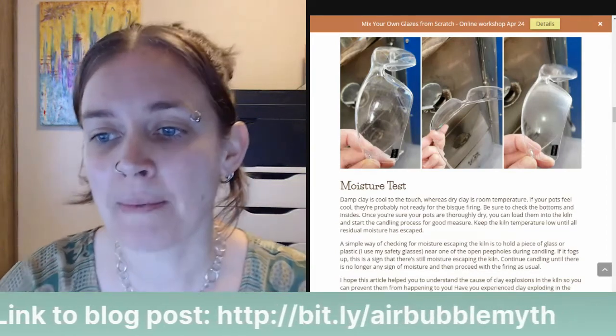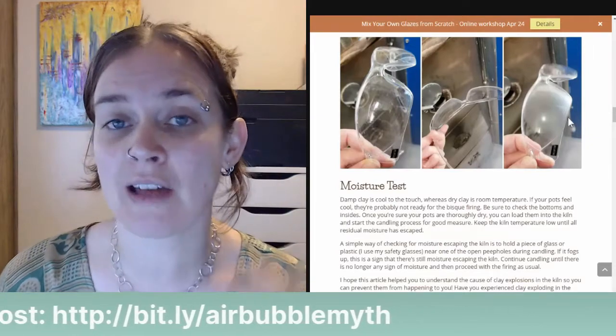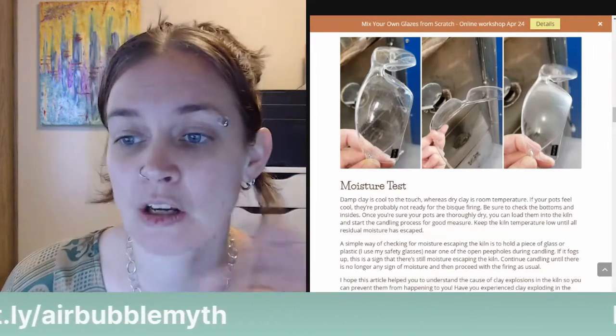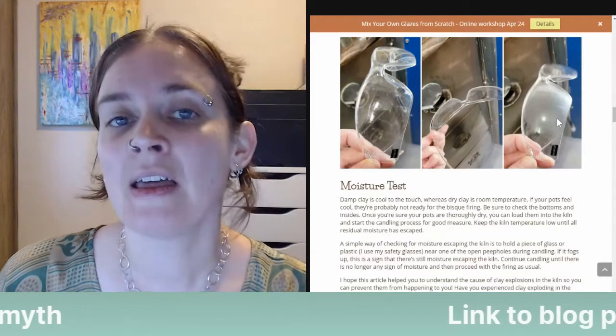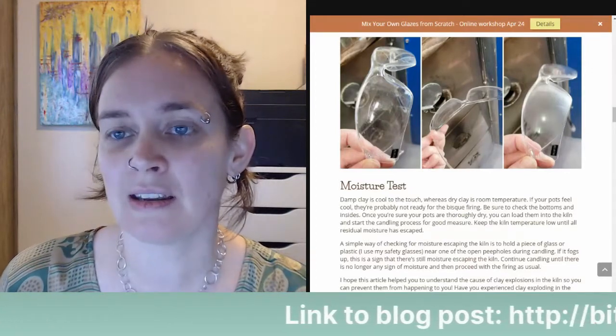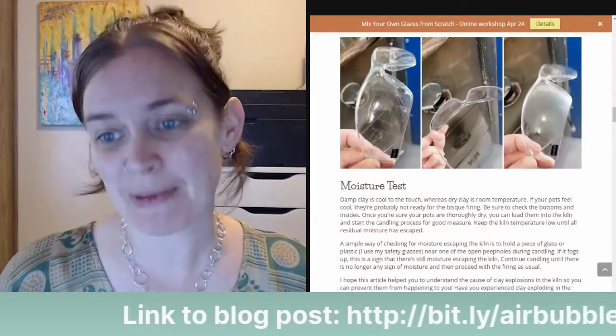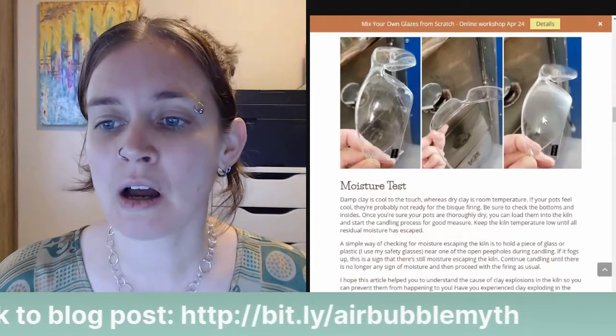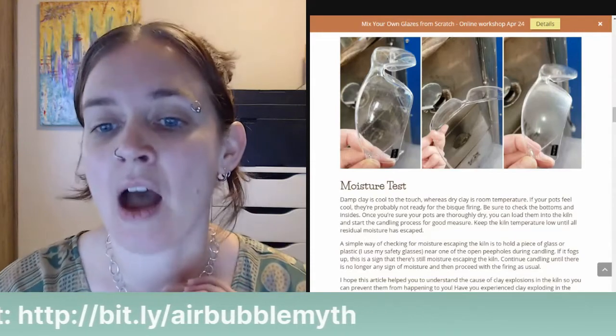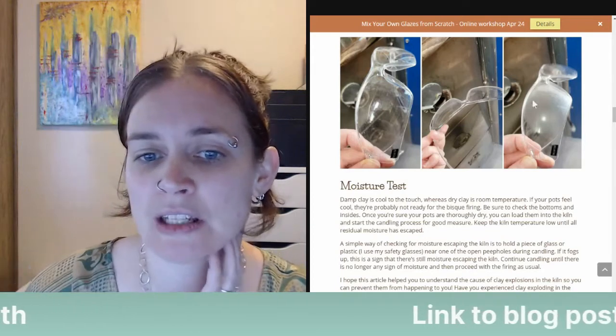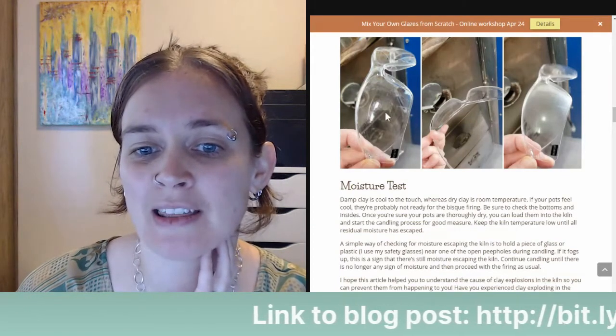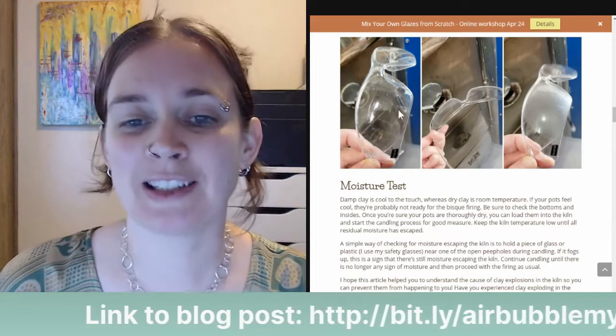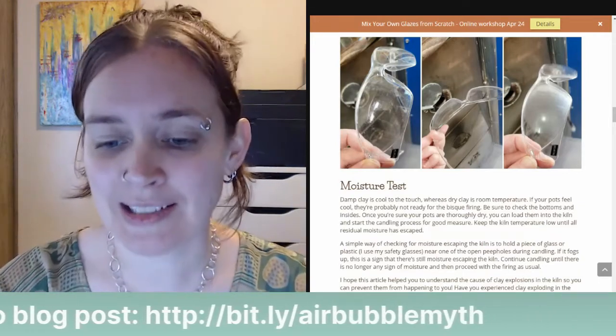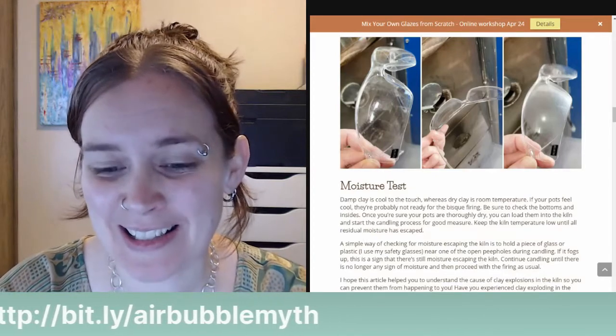And so if you are still seeing your glasses or your mirror or whatever fogging up, then that's a sign that moisture is still escaping, and you need to keep your kiln on low until there's no longer any sign of moisture coming out of your pots. Once your glasses look like this after holding them in front of the peephole, that is a good sign that you can kick it into high gear and increase your bisque firing temperature.